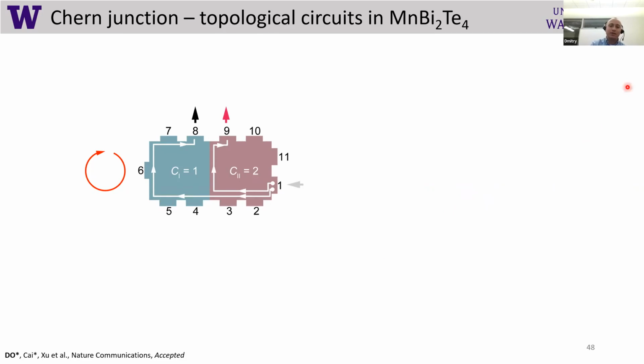For that, we take this device, which has 11 electrodes. To test and map out the location of edge states in our material, one way to do it is to send current from one terminal and detect it at different terminals and different domains. So let's see how it works. We have an assumption here. Actually, not an assumption, we have a measurement of Chern number. Chern number is 1 and 2 on these two domains. And we have an assumption that the current will flow in the following way according to these white lines.